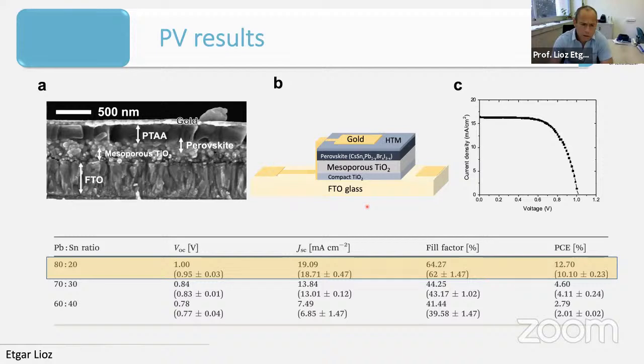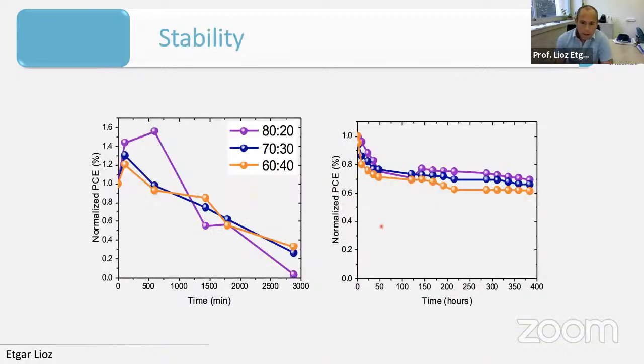Finally, we introduce them into devices, into solar cells, and observe very nice performance, more than 12% with 1 volt VOC. This was something promising to observe with all-inorganic perovskite, with, let's say, a reasonable stability, not something that degrades in 2 minutes. Here you can see the stability of those. This is a full device stability. As you can see, it has some degradation in the first few hours, but then it stays quite stable for a much longer time.